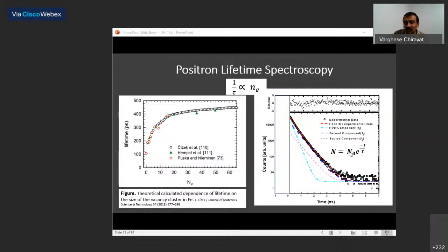So one, it will give you the information on what kind of defect is present in your material. Two, the intensity of each of these components, how much tau1 is present, how much tau2 is present, will tell you what is the defect intensity in your material. Say, for example, what concentration of mono vacancies are present, what concentration of di vacancies are present, and so on. So positron lifetime spectroscopy can give you the defect density and defect type. And this is extremely important for a whole lot of material science projects. And some of you who are in research can think of it, because defects play an important role in electronic and optical properties of the material, and hence it is very important to know what is the defect structure of your material. Okay? So you can use positron lifetime spectroscopy if the need arises.